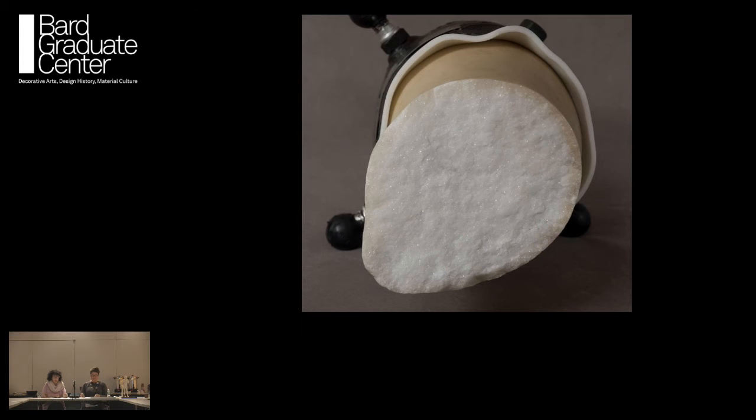These fats, which were analyzed by Adriana Rizzo from our Department of Scientific Research, turned out to be largely tallow and are not readily soluble, guaranteeing that this discoloration could not be safely extracted from the stone. The unevenness of application of these fats over the years resulted in an uneven tonality on the sculpture's surface. So he knew that if the marble were cleaned to the same degree everywhere, there'd be a risk of overcleaning in some areas while other areas might end up looking darker.